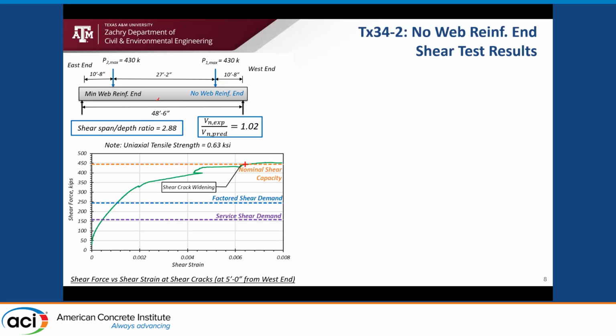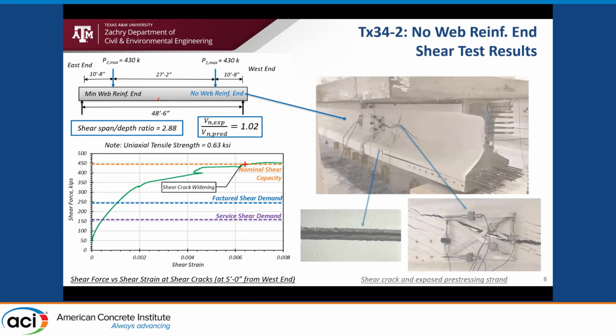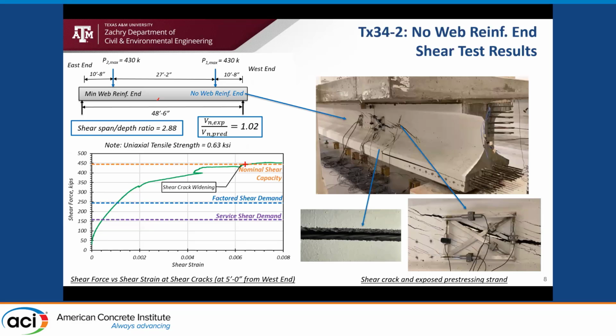The next specimen was, as I mentioned before, stronger in tension and had better shear performance with about 444 kips shear strength. We did not run into any issues of premature shear cracking, and therefore, after the flexure test was done, we tested the whole beam under shear, and sure enough, the end with no web reinforcement failed first under shear, and we observed typical web shear cracks in this region. Along with that, we had interface slip at the bottom flange, and a prestressing strand was exposed.